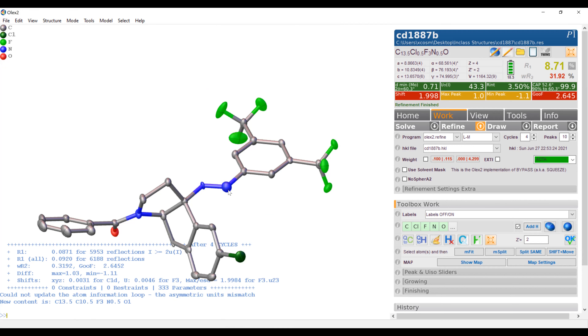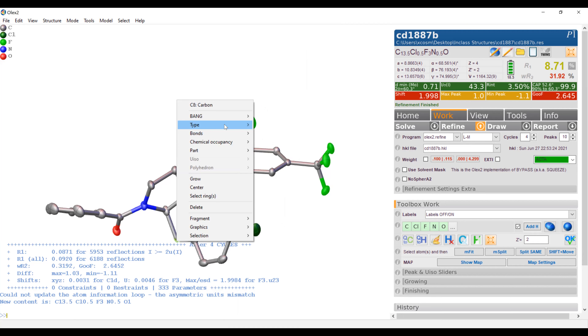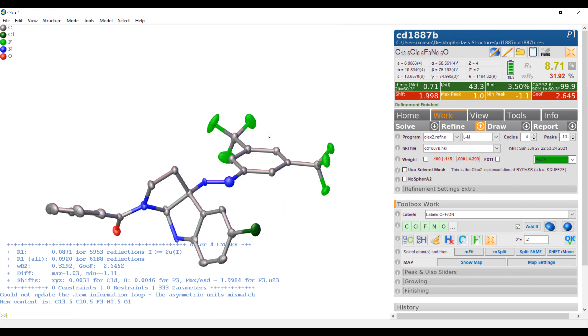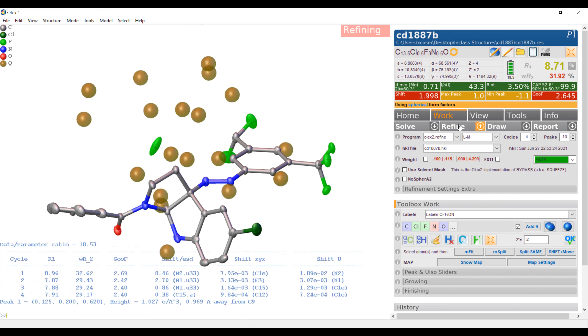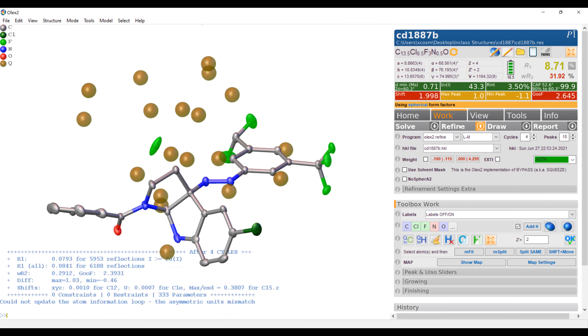Here we have an azide. Right-click, check the bond distance — that N-N bond is about 1.229, so it's like an N-N double bond. We also have a small thermal ellipsoid at the atom labeled C8, so let's right-click and change this to maybe a nitrogen as well. We think it looks something like this, and again we're going to refine. We got a better model for the data.